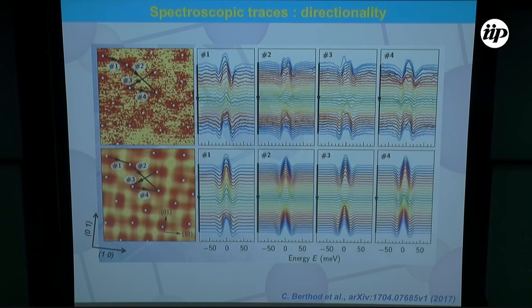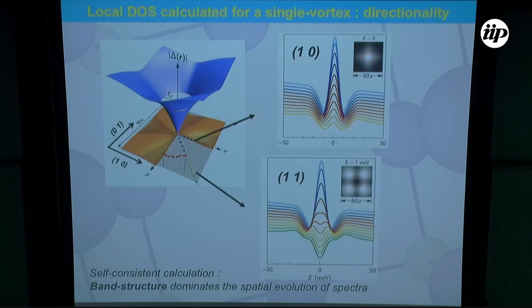And actually the same model, with the same procedure and considering the same traces, 1 and 4, is also providing the small spectral weight at 0. So it really means that depending on the direction we consider, the decay of this zero bias anomaly is different. And this can actually be well illustrated in the case of a single vortex.